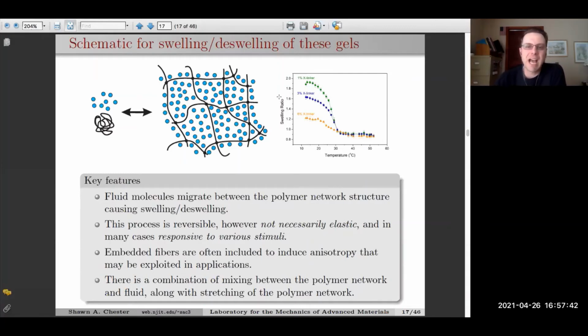And some data that we have from my buddy Hoan, that video I showed at the beginning of the dumbbell that shrinks as you increase the temperature, here's some measurements that he took. As you go from 10 up to 50-ish degrees Celsius, the swelling ratio, he's basically measuring the diameter as it changes.